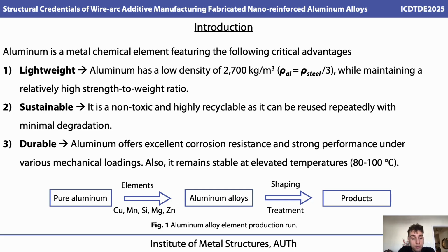The main process to produce a product from an aluminum alloy is illustrated in figure 1. As you can see, pure aluminum is alloyed with elements such as copper, manganese, silicon, magnesium and zinc, and then we get what we know as aluminum alloys. Then we shape these aluminum alloys into our products. We treat these products with heat treatment most of the times, and then we get our final aluminum product.